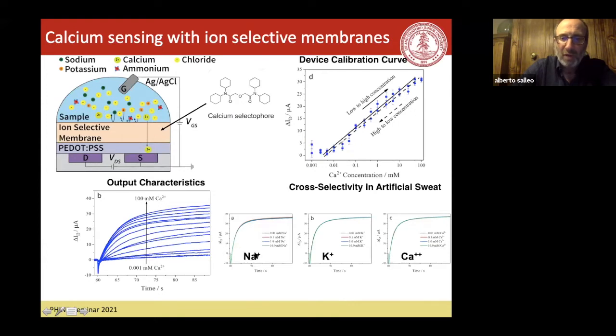And if I change the concentration of sodium or potassium, I actually don't get a change in the current. And so you can see that I can then calibrate my sensor as a function of concentration of calcium, from low to high and high to low. So this is also important to show. This is a reversible sensor, and so it works as a reversible sensor.